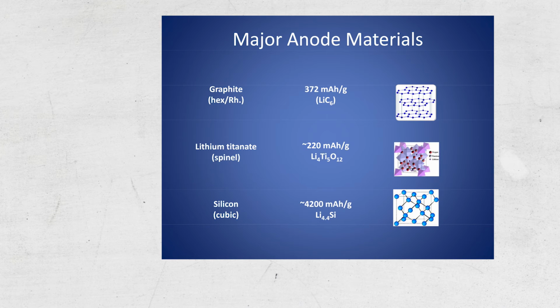All right, the other prospective anodes are the lithium titanate. With this formula, the capacity per gram is about 200, and it has the spinel structure, and others like silicon, very high capacity, but there are some issues with, I would say, efficiency and also the life of this anode. But anyway, these are only the major ones, and of course, people are very, very creative in modifying these anodes by doing some substitution or modification on the surface and so on so as to improve the performance. But still today, if you buy a battery, the most likely chance is that you find either graphite, maybe 95%, and lithium titanate 5% as the anode.